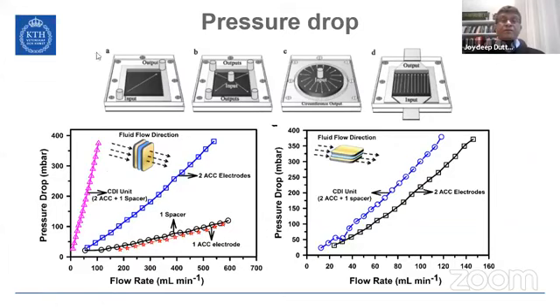However, what we can determine from here is that this is a flow-through system that we follow, and that's the uniqueness in our CDI system compared to others being published by other groups. On the other side, the flow direction is like this. In that case, one is getting just the surface to absorb the salt ions. In our case, the water goes through the electrodes, and these electrodes are typically 1,000 square meters of surface area per gram. Like the activated carbon cloth I showed you is about 1,100 square meters per gram.